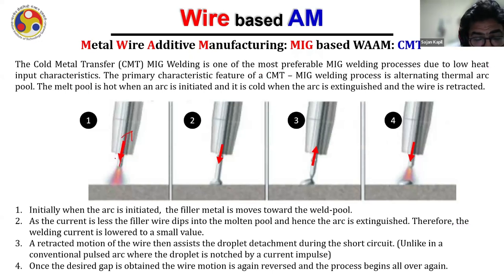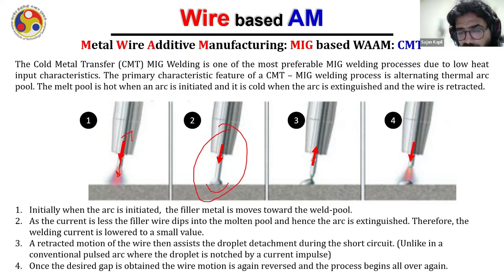So they see here, the wire is going forward, it's touching the substrate, short circuit happened. As soon as short circuit happened, the surface tension between the melt pool created on the substrate and the drop generated at the tip is high, and they got better adhesion and got stuck here. And you pull the wire back. Of course, if you pull the wire back very fast, what will happen? It will leave the drop behind.